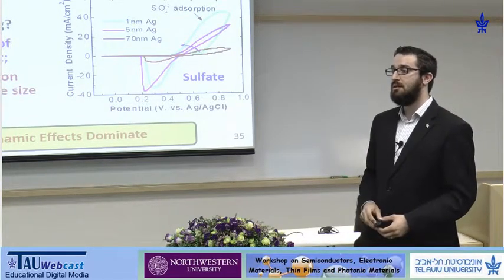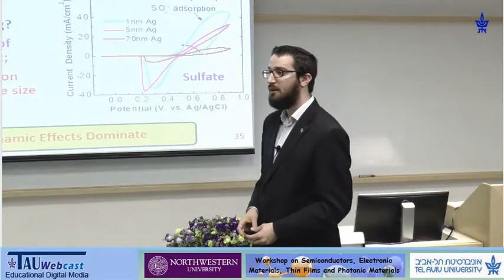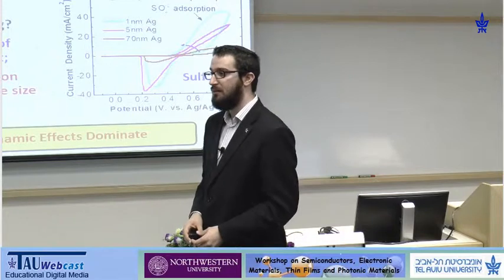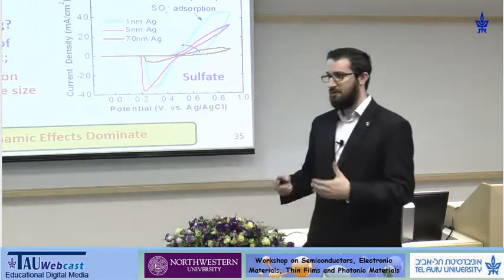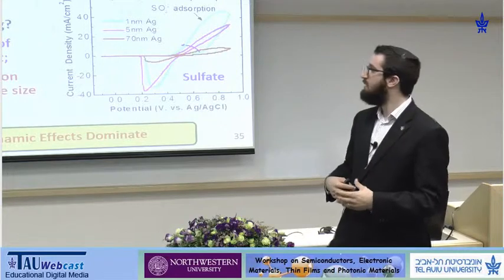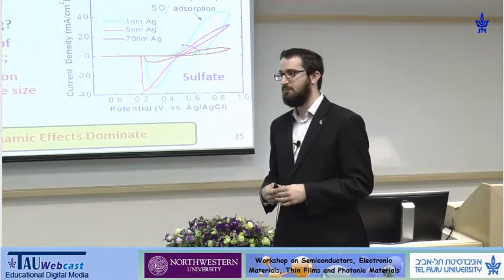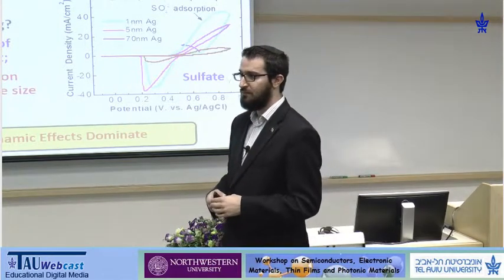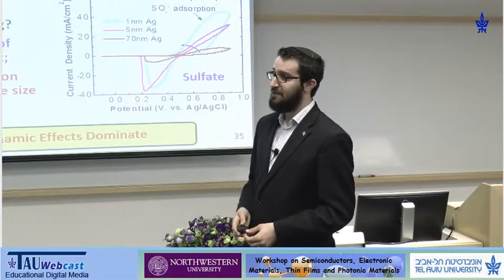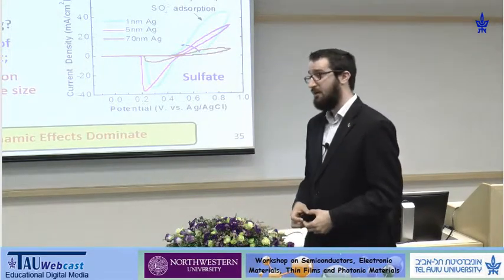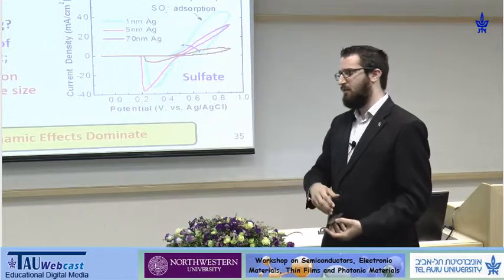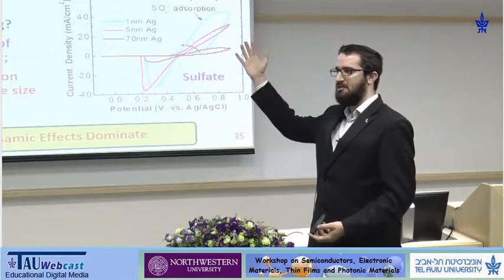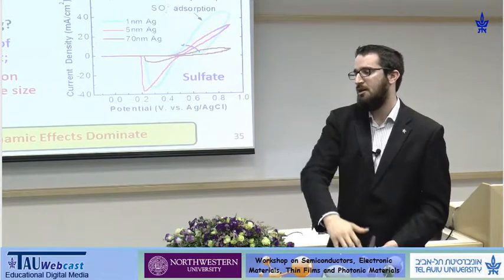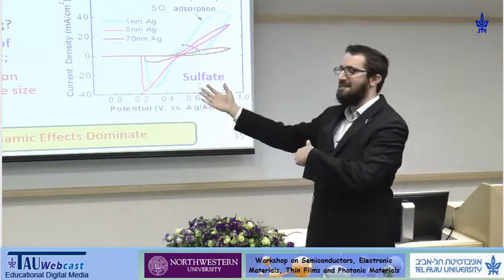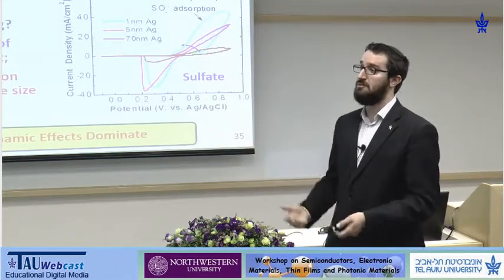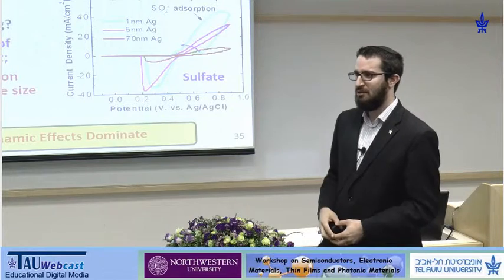Yes? Are you at a high enough temperature that when you do the adsorption, you can actually change the Wulff shape to different facets? So right now, you're talking about the faceting of the surface? Yeah, if you have a small particle, it would be easier to change the Wulff shape into another shape than for a bigger one. So right now the faceting is done at room temperature. We're not doing it at elevated temperature. And for the mechanism of the faceting, we're looking at the adsorption of oxygen and then throwing it into the hydrogen absorption region, which effectively creates metal oxides and then the decomposition of those oxides. And this will lead to surface reconstructions. And there are a few other mechanisms in the literature.